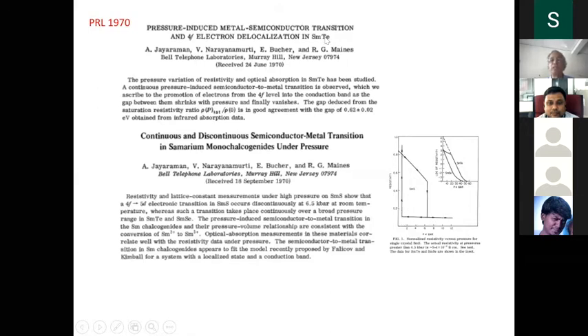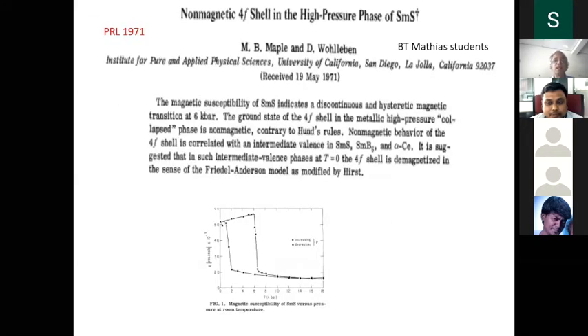However, when it comes to samarium selenide and telluride, you could see the same thing happen, but continuously. Here, there is a sudden change in electrical resistivity, a huge change in electrical resistivity under pressure. In one case, it is sharper. In other cases, it is sort of normal. When they studied the so-called high pressure phase of samarium sulfide, they behave exactly like cerium, in the sense that at high temperature you see magnetic susceptibility, Curie-Weiss like, and at low temperature it is non-magnetic. And then the actual explanation was proposed in 1971 by two scientists in California, who were the first to propose that the f electrons get demagnetized.